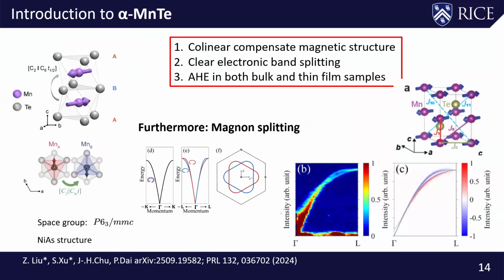So let me give additional evidence for why this system could be a real altermagnet. Transport measurements have suggested that it could be an altermagnet, and another type of measurement, angle-resolved photoemission spectroscopy, shows a splitting of the electronic band. But I'll try to emphasize the neutron scattering experiment, actually done not by our group but by a group in Japan, which has shown clearly a splitting of the magnon band at some point between the gamma and L point in reciprocal space.